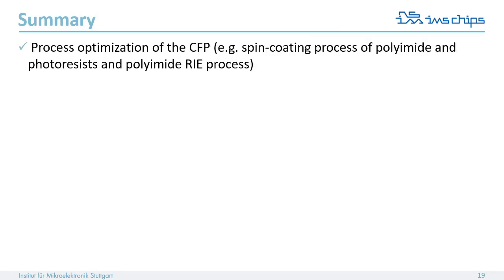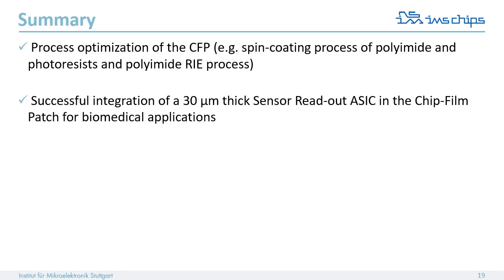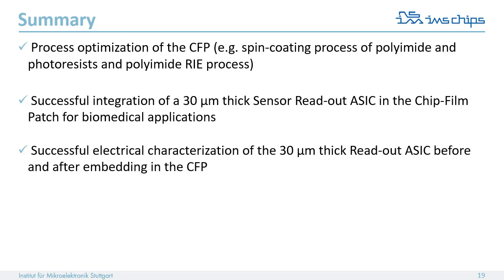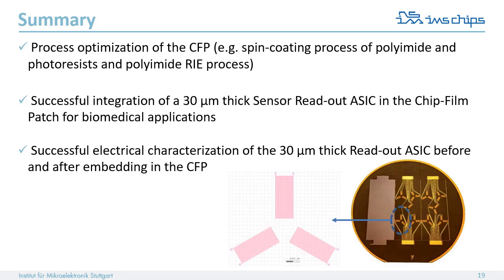For the conclusion, I will briefly summarize our results. I have discussed the benefits of the ChipFilm Patch process optimization, such as the adaptation of the spin coating parameters, which has a positive effect on the polyimide RIE etching. We have successfully integrated the 30 micrometer thick sensor readout ASIC in the ChipFilm Patch, which is now ready for biomedical applications. The successful functionality test of the 30 micrometer readout ASIC before and after embedding in the ChipFilm Patch shows the same signal amplitude. And in addition, we have already finished the strain gauge sensor, and we will start right now with the characterization.